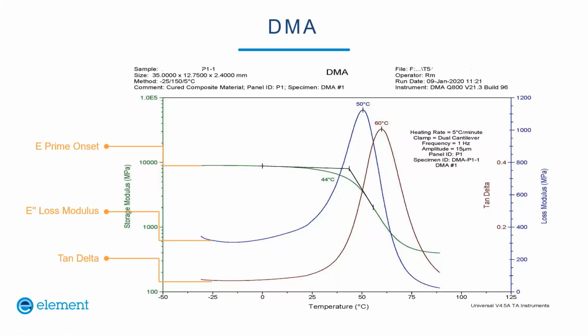So this sample happened to be a room temperature cure epoxy that was post-cured, and we can see all these temperatures are just above room temperature. Moisture will tend to lower Tg, and we'll get back to that later, but it's a good time to mention that consistent drying or conditioning is needed to create reproducible measurements. But when you dry or condition the samples, it's important to stay well below the cure temperature of the material. Otherwise, you're going to be imparting additional post-curing to the specimen that the actual part might not see.